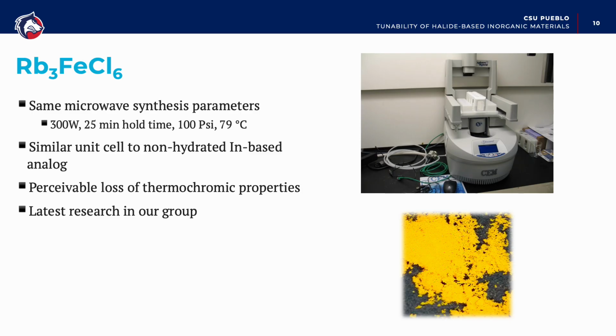I set out to answer this question with my research, and that is exactly what I am doing now in the lab. So I applied the same parameters with the microwave instrument as before: 300 watts, 25-minute hold time, 100 psi, and 79 degrees Celsius.